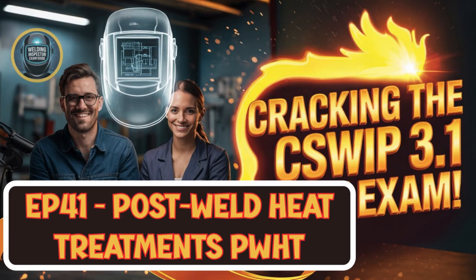Which is why people often just call it stress relief, right? Exactly. That's the most common term, because reducing residual stress is usually the primary goal. And the way it works is pretty neat, actually. At those high PWHT temperatures, the steel's yield strength, its resistance to bending or stretching permanently, gets much lower, becomes more pliable, let's say. This allows the atoms in the steel structure to kind of shift around, rearrange themselves just enough to release those locked-in stresses. It's like a muscle finally unknotting.